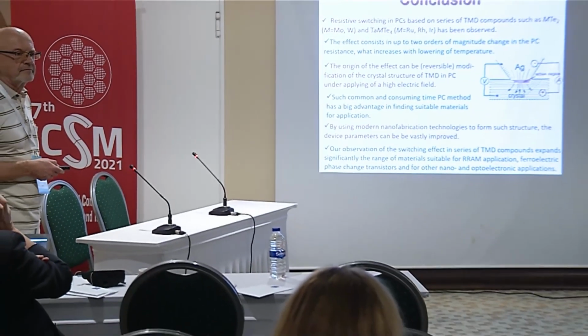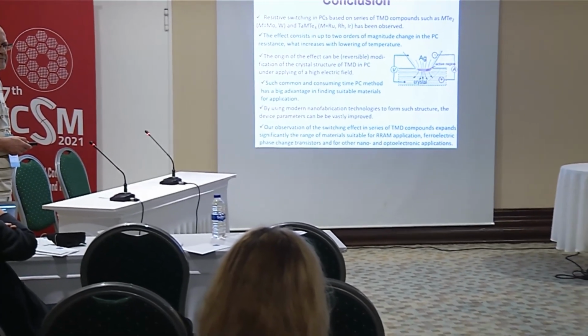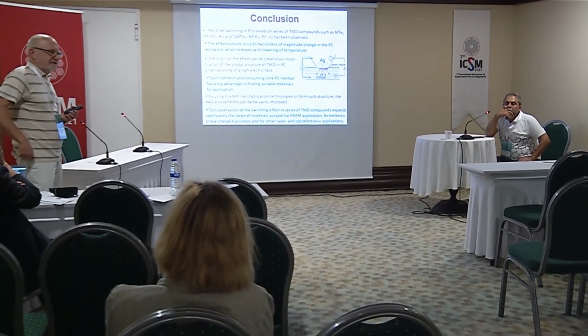As far as I understood, you used the in-plane contact geometry with the current flowing along the C direction. Am I right? Generally, yes. But it's difficult to know what is the direction of current in point contact, because this surface is not atomically flat. So probably there are also some steps. The current can flow not only in the C direction but also in the B direction. But nevertheless, the effect is present. Thank you.